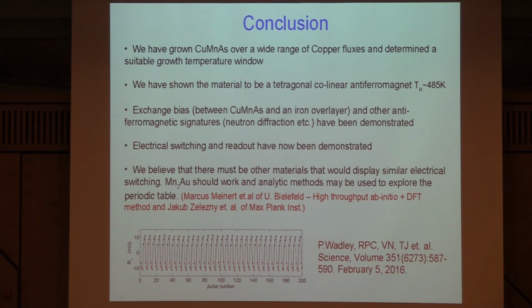Okay, so this is my conclusion. We have, I believe, grown copper manganese arsenide over a wide range of copper fluxes and seen the behavior, the fact this stuff really wants to grow. It rejects the excess material which grows precipitates, but basically between the precipitates and good quality material. We've shown it to be a tetragonal, collinear antiferromagnet. That's the Néel temperature. We've seen exchange bias with iron overlayer, other anti-ferromagnetic signatures, neutron diffraction, etc. Now we've done electrical switching, which is nice.